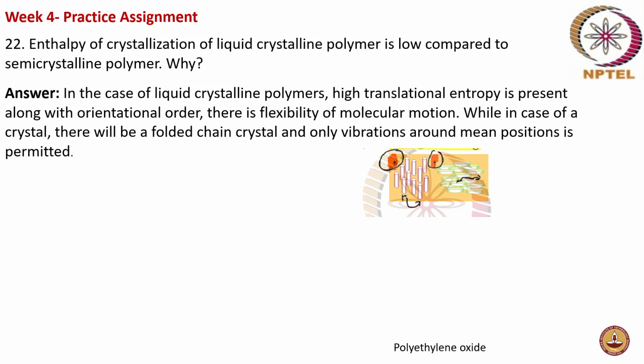Whereas if you consider a semi-crystalline polymer, you have the folded crystal chain. Okay, and in this folded crystal chain, once the chain has folded and formed lamella and all, there will not be any kind of motion. Only vibrations will be possible. So the energy absorbed or dissipated during these vibrational changes will be very minimal, whereas during translational changes will be comparatively more. That means when you have a phase change from a crystal to melt, there will be a larger energy associated with that process in case of a semi-crystalline polymer.